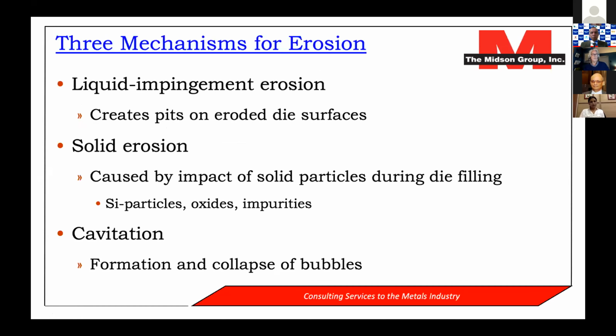Then we can also get solid erosion. This is caused by the impact of solid particles during die filling, hitting on the die surface. Where do the solid particles come from? Obviously, silicon particles pre-solidified in the aluminum alloy. Oxides can be very hard, very abrasive, and they can cause quite serious erosion. And then other solid impurities in the aluminum alloy.